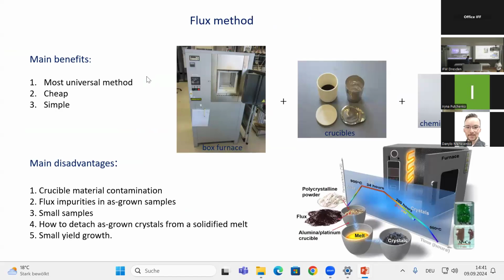So first, the flux method, it's the cheapest and simplest one. You simply mix your material in powder form with the flux material, place them in a crucible, and heat it up. At a certain temperature you melt your flux material, and then your molten flux dissolves your material, and after saturation you start the spontaneous crystallization by slow cooling. And so basically that's all.